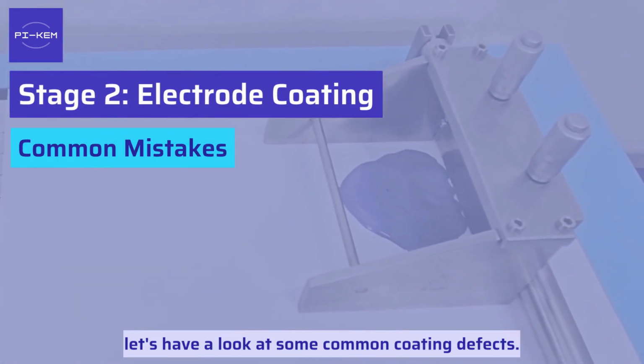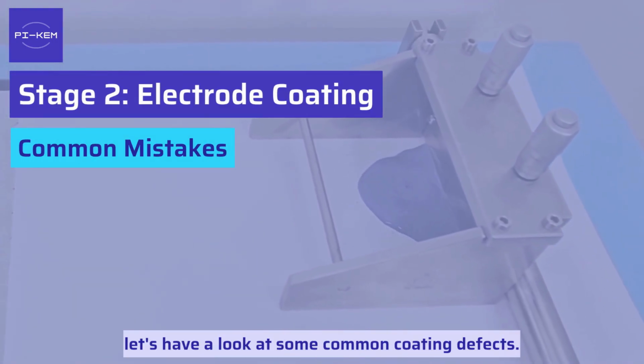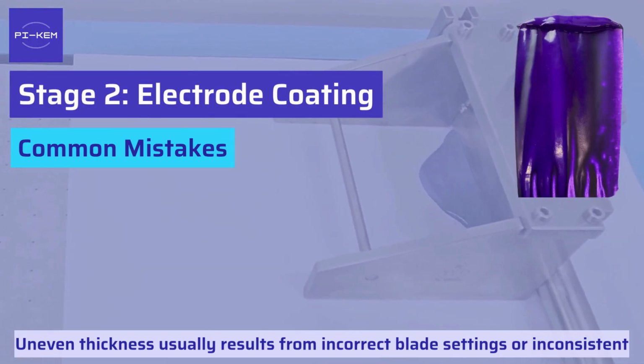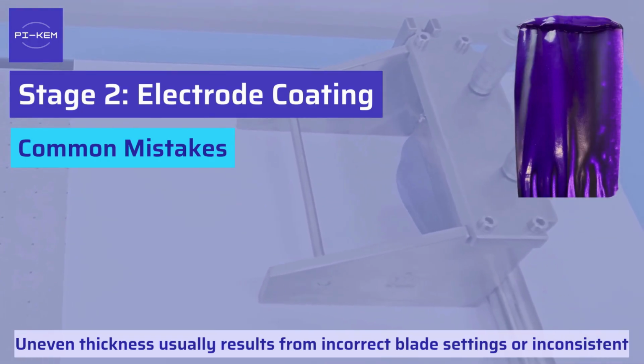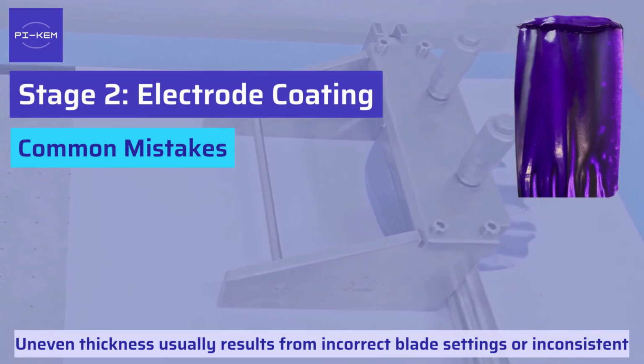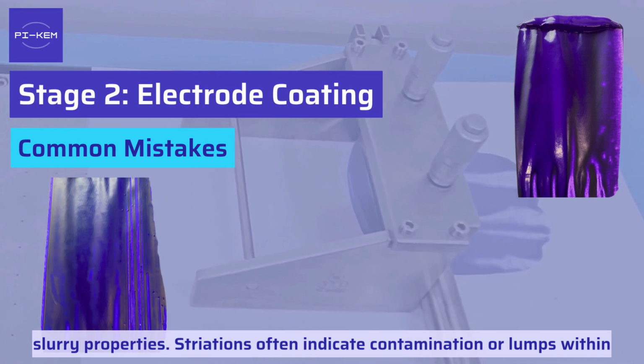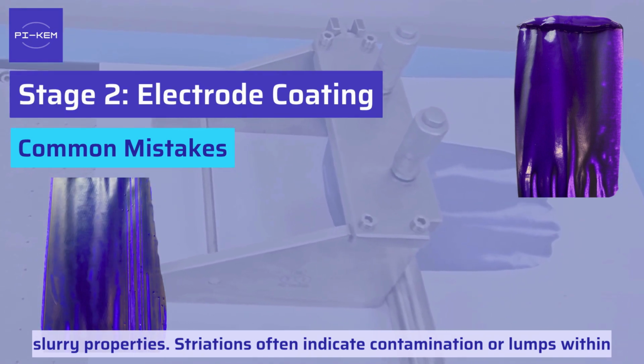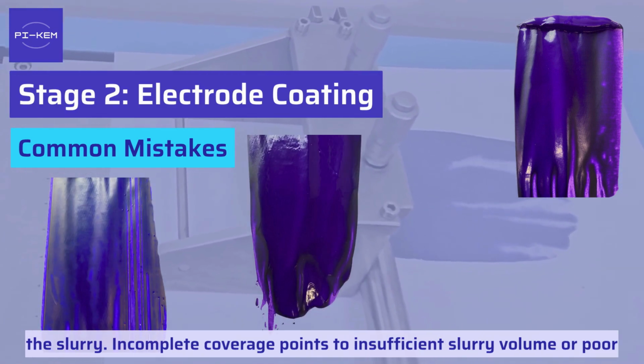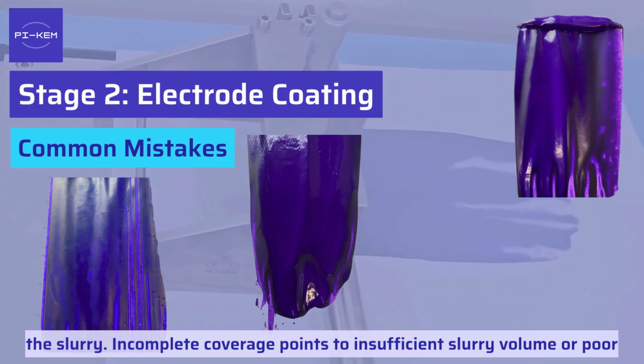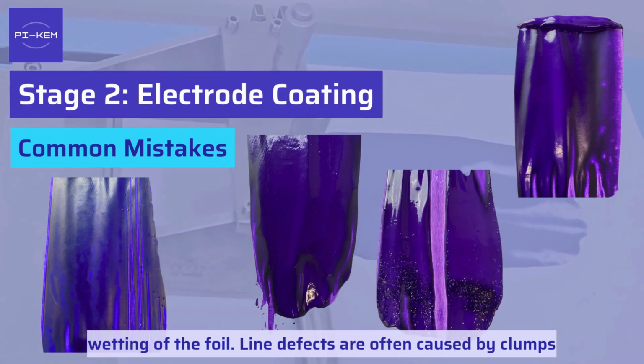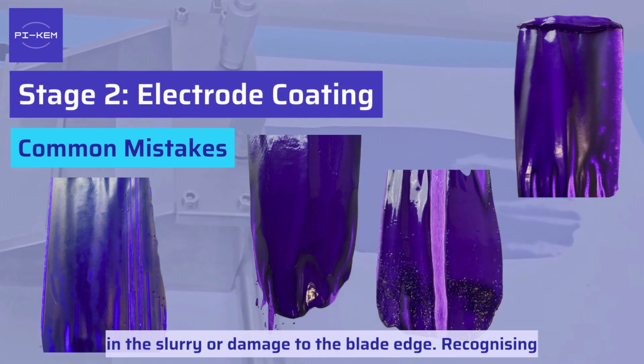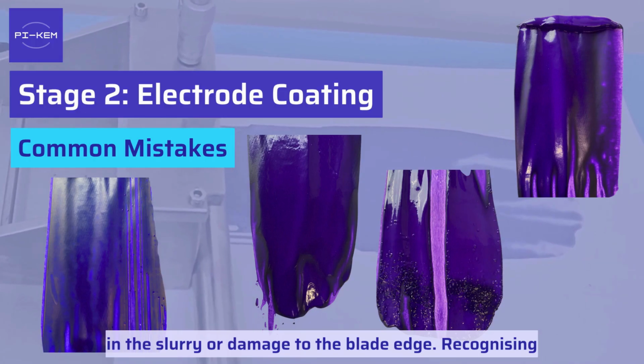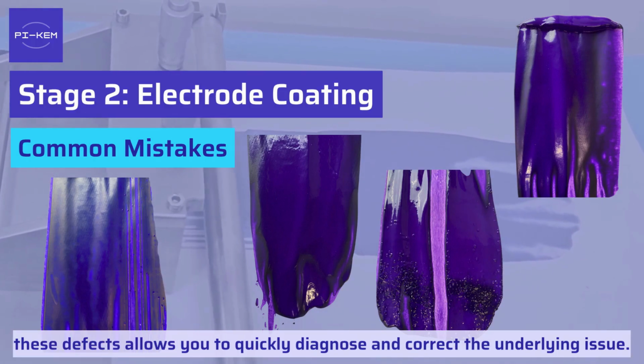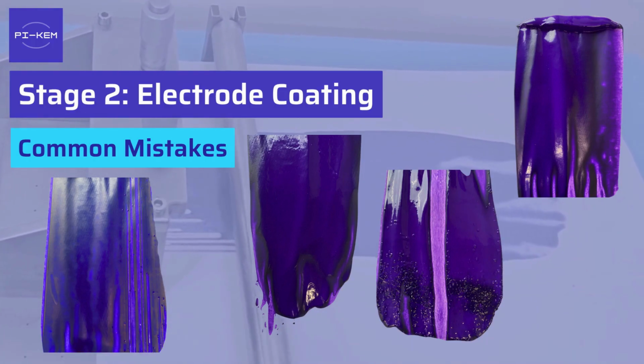To wrap up this video, let's have a look at some common coating defects. Uneven thickness usually results from incorrect blade settings or inconsistent slurry properties. Striations often indicate contamination or lumps within the slurry. Incomplete coverage points to insufficient slurry volume or poor wetting of the foil. Line defects are often caused by clumps in the slurry or damage to the blade edge. Recognizing these defects allows you to quickly diagnose and correct the underlying issue.